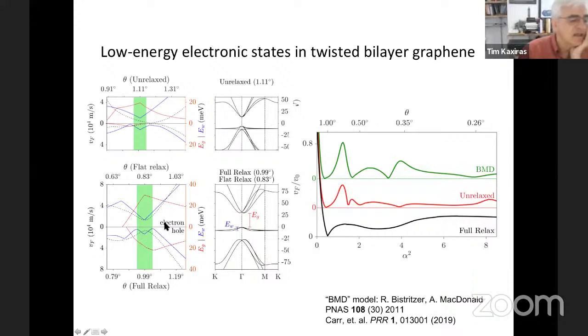And you see the results for the electron up here and the hole. So there's definitely a broken electron hole symmetry. According to this set of calculations in this picture, there's no electron hole symmetry here. It's broken. And the black dashed line here is the Fermi velocity. So this is the twist angle.